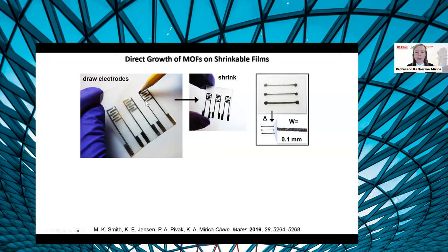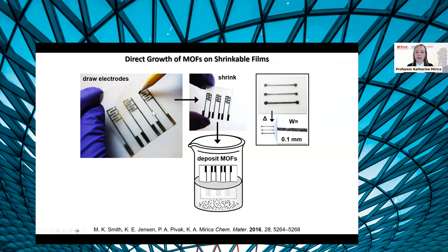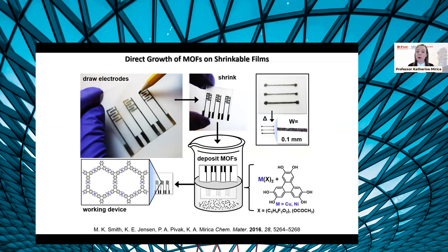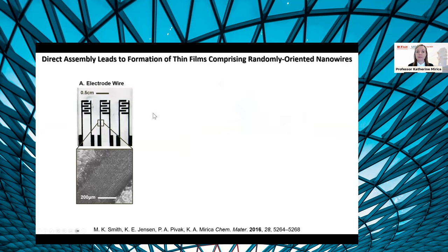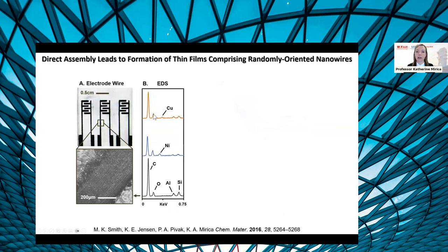So our electrodes fabricated by this method have feature sizes of about 100 to 300 microns. And then we can take this electrode chip and simply dip it into the solution phase precursors of the metal organic framework and allow the framework to grow directly into the device. So this is our electrode wire as imaged by electron microscopy.